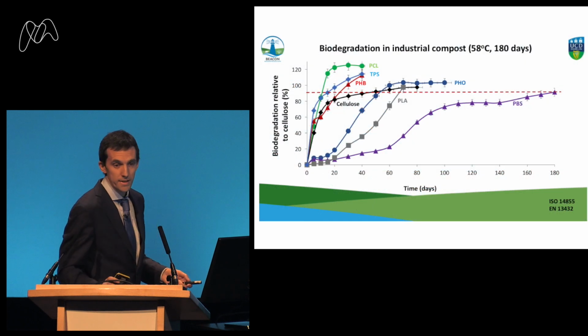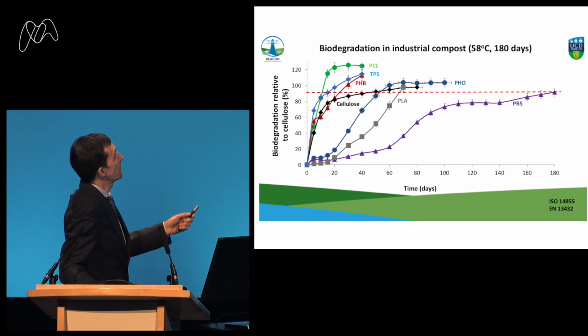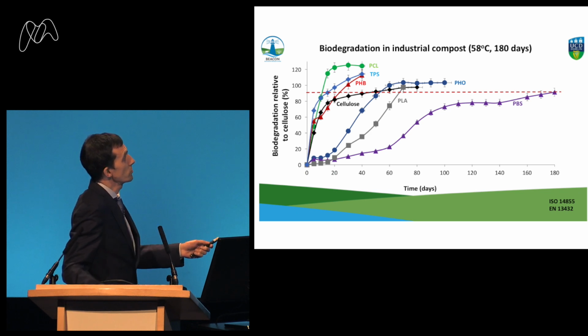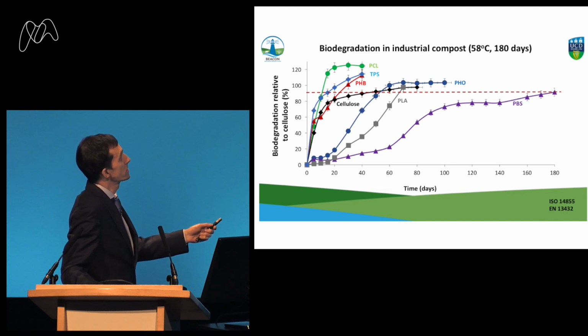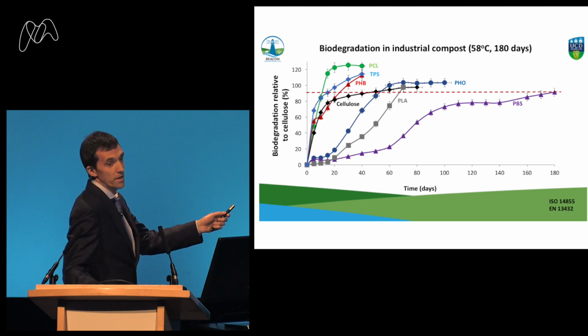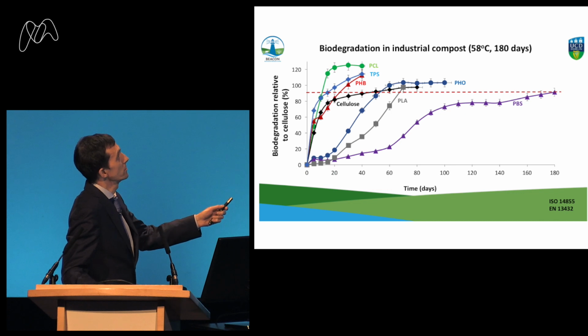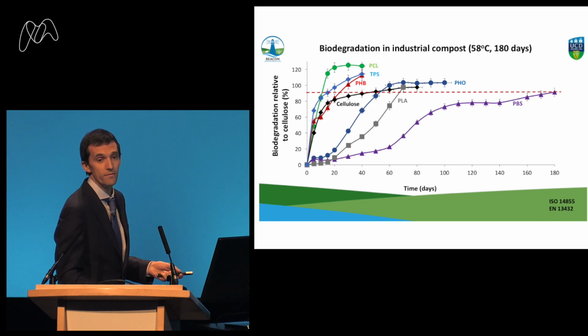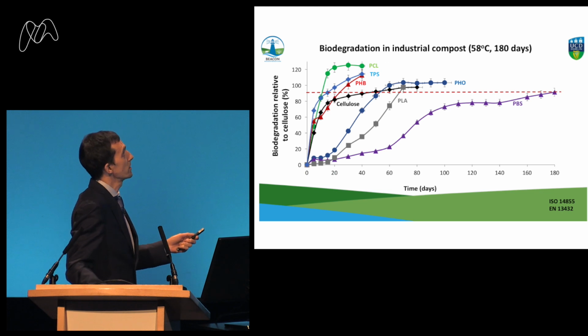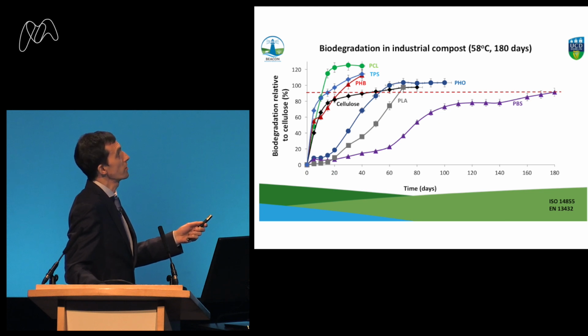What I'm showing you here, there's a lot of data, and I'll just bring you through this. I'm showing you biodegradation relative to cellulose, and I'm showing you the time in days, and we have up to 180 days. And here's cellulose. So cellulose rapidly degrades within the first 10 to 20 days and then slows down, and that's a classic cellulose degradation curve. What we see is polycaprolactone, petrochemical based, is highly biodegradable and actually biodegrades more than cellulose. TPS, which is starch based, thermoplastic starch, also rapidly degrades, and polyhydroxybutyrate, produced by bacteria, also degrades rapidly.